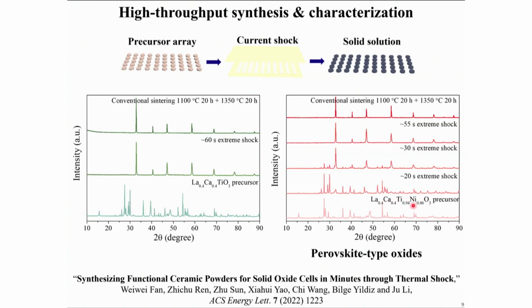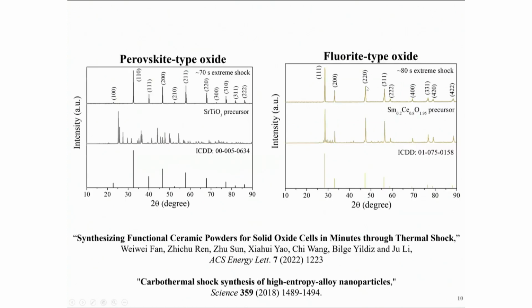Traditionally, this oxide in the furnace would take up to 40 hours to get this phase-pure product. But with extreme processing, such as carbothermal shock, plasma synthesis, or pulse light synthesis, we can produce these phase-pure powders in just 55 seconds. And this is then coupled with high-throughput characterization to find the optimal synthesis recipes. So that was a perovskite-type oxide, and this is samarium-doped ceria. It's a fluorite-type oxide.